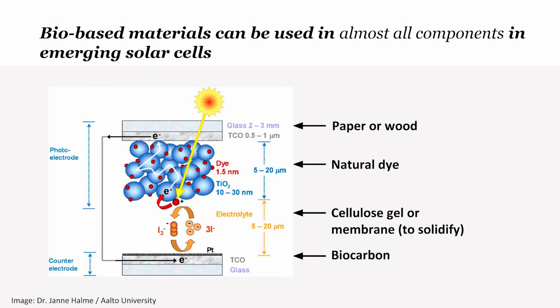So typically, emerging solar cells have three main components. They have the photoelectrode that absorbs the light, then they have the counterelectrode that returns the charge, and there's a medium in between that allows charge only to go one way. Next, let's look at how these components could be replaced with bio-based alternatives. So firstly, the commonly liquid electrolyte could be solidified by utilizing cellulose, gels, or membranes. These materials have also improved the efficiency of the device and also reduced the number of possible leakage pathways.